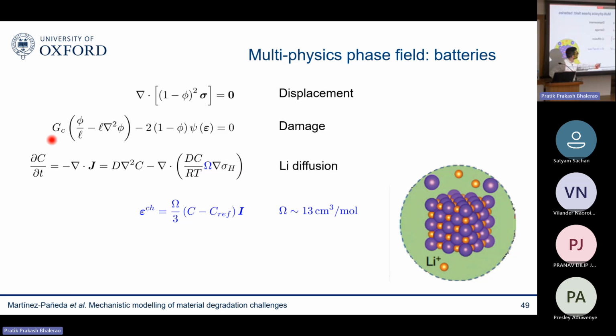Here you notice that the lithium concentration does not degrade your toughness. People have done atomistic simulations and have seen a little bit of degradation, but very little, nothing to do with hydrogen. Hydrogen really makes it easier to break bonds. It's not the case with lithium. And the other thing that you see is that you have these chemical strains that are very small in hydrogen, but are very prominent in lithium. And this comes naturally out of the model.